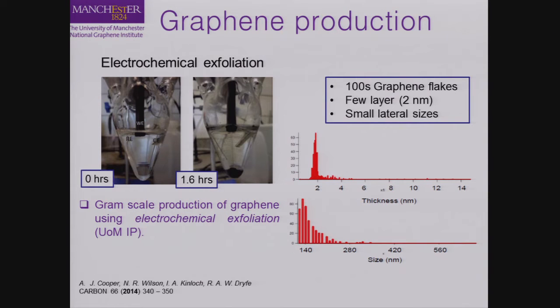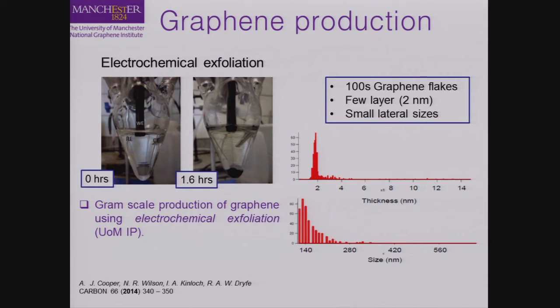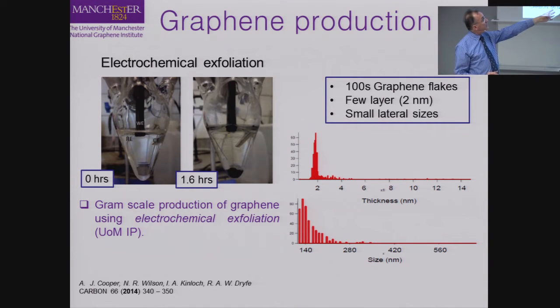And at the moment, we produce few-layer graphene flakes. They are few layers thick. Small sizes, you can see there the distribution of size, anything between 140 to 300 nanometers, and the thickness around 2 nanometers, or less, or slightly more, few layers.